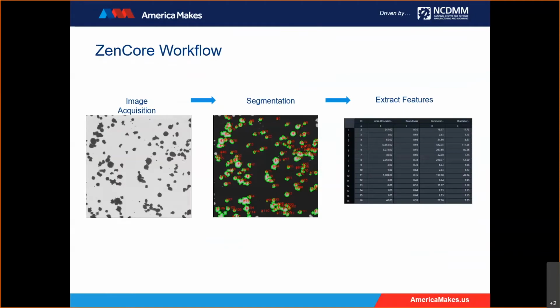When we do light microscopy, we're trying to determine the powder morphology by measuring particle features like the area, diameter, circularity, and aspect ratio. We're trying to understand which of these characteristics, or which combination, affects the powder spreadability and the flowability. We know that ideally spherical powder particles will spread and flow better when raked during the build, but most times we don't have ideal powder. Depending on the method of atomization or your recycling stage, you may also have spherical particles with satellites, elongated particles, or spatter.